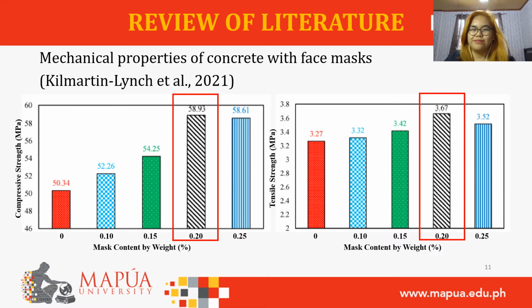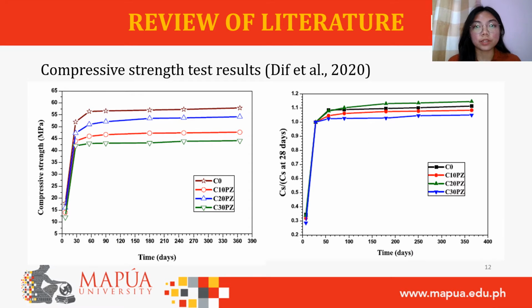face mask. A study by Dif and others discovered that adding about 20% volcanic ash as partial replacement to concrete materials exhibited the nearest compressive strength to the reference concrete, while it has the highest strength gain for the period of 28 days. This increase in compressive strength can be attributed to the delayed pozzolanic reaction of pozzolan with cement hydrates, forming calcium silicate hydrates, which acts as binder.